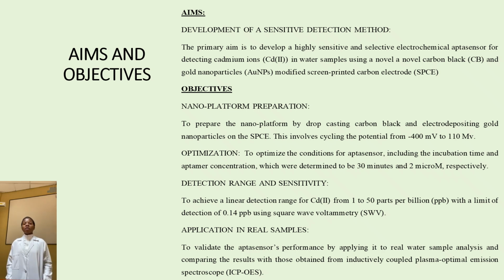Firstly, we have nano-platform preparation: to prepare the nano-platform by drop casting carbon black and electrodepositing gold nanoparticles on the SPCE. This involves cycling the potential from -400 to 110 mV. Secondly, we have optimization: to optimize the conditions for the aptasensor, including the incubation time and aptamer concentration, which were determined to be 30 minutes and 2 micromolar concentration, respectively.